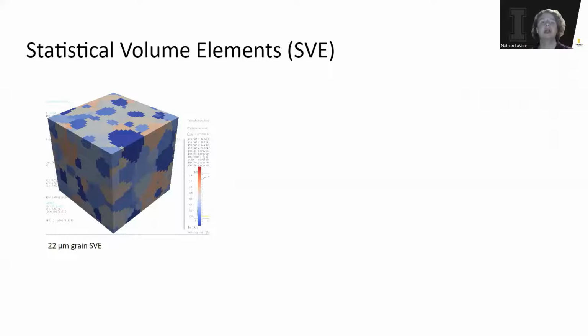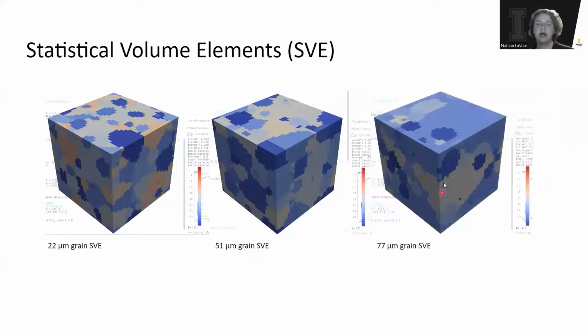The statistical volume element takes into account the variability in microstructure, where a typical representative volume element assumes the average value for each grain. This can be seen in the variability of the model crystal. You can see that there's wide variation in crystal sizes and orientations and overall sizes and shapes. The grain size also has an effect. As you increase the average grain size of the crystal, the average grain inside the image becomes larger, and there are fewer of them because they are on average a larger crystal.